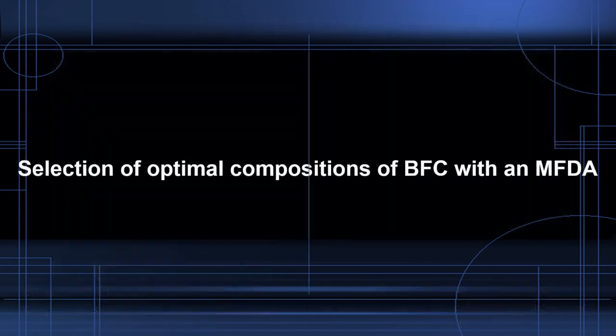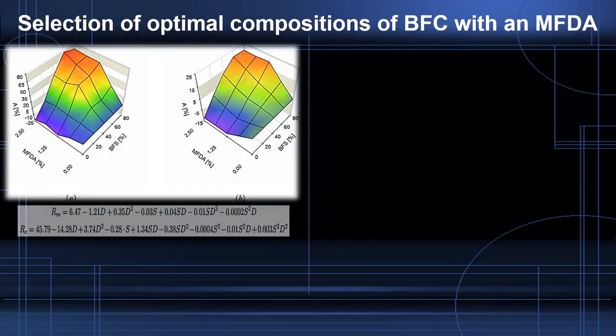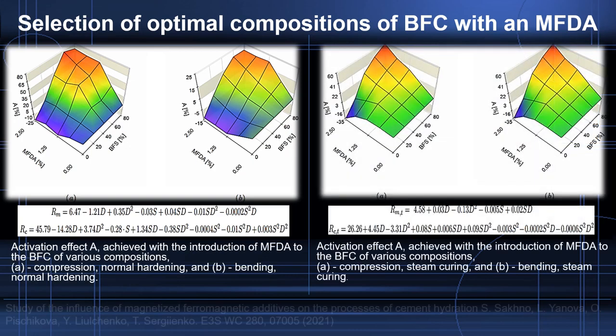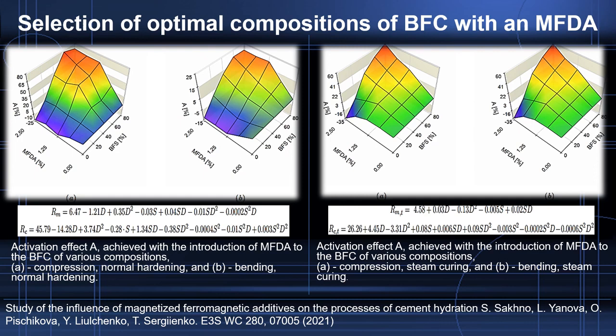Studies of the strength characteristics of binders with different BFS and MFDA ratios were carried out to identify the optimal amount of MFDA in cement with different BFS content. Investigated binders had in their composition, in various series, from 0 to 2.5% of MFDA and from 0 to 80% of BFS. The results show that with an increase in the proportion of BFS, the need for MFDA increases, and the activation effect enlarges. At the same time, an increase in the amount of MFDA added to BFS-free cement causes a drop in the activity of the binder. The reasons for this regularity were studied by us and described in a previous work.